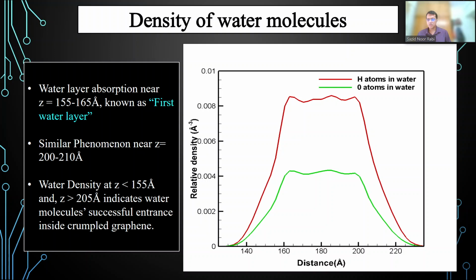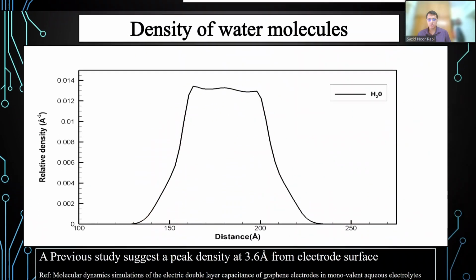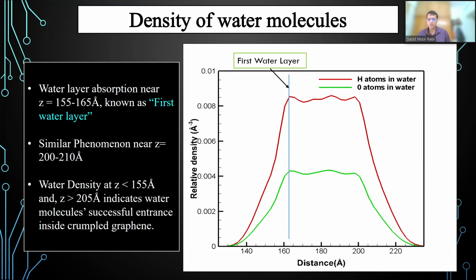Here we can take a better look at the density profiles of water. We can see a surge of water density near 165 angstrom and 210 angstrom. Both are called the first water layer. In literature, the hydrophobicity of graphene is thought to be responsible for this formation, due to the porous structure of graphene. We can also see some water molecules inside the electrode regions.